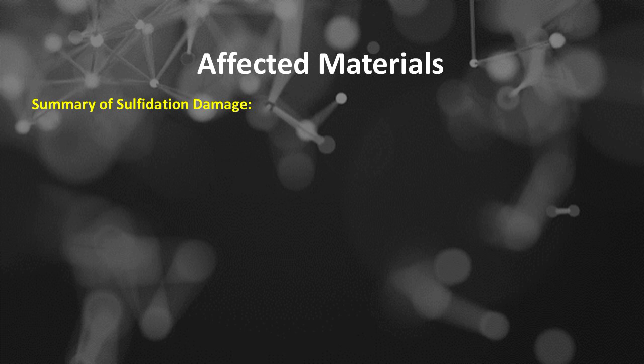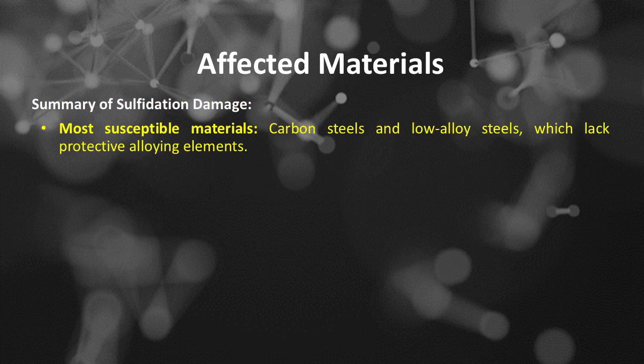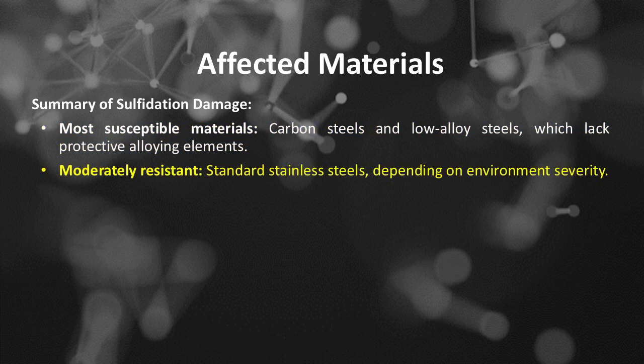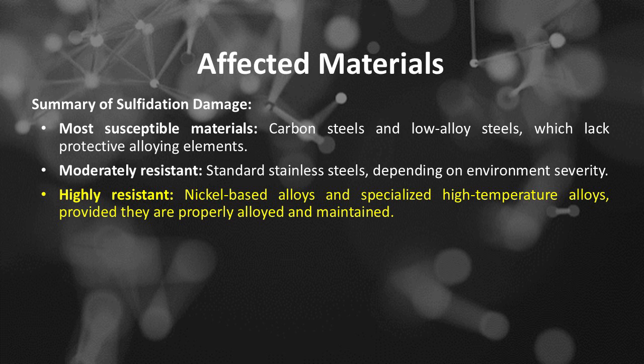Summary of sulfidation damage. Most susceptible materials, carbon steels and low alloy steels, which lack protective alloying elements. Moderately resistant, standard stainless steels, depending on environment severity. Highly resistant, nickel-based alloys and specialized high-temperature alloys, provided they are properly alloyed and maintained.